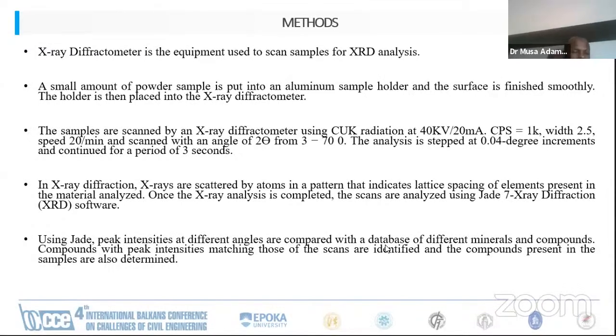In X-ray diffraction, X-rays are scattered by atoms in a pattern that indicates lattice spacing of elements present in the material analyzed. Once the X-ray analysis is completed, the scans are analyzed using JADE X-ray diffractometer software. Using JADE, peak intensities at different angles are compared with the database of different minerals and compounds. Compounds with peak intensities matching those of the scans are identified and the compounds present in the samples are determined.